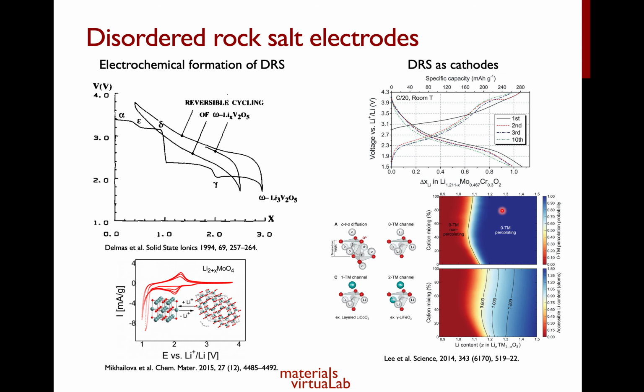Okay. Now, in recent years, the disordered rock salt materials have garnered increasing interest as potential electrodes for lithium-ion battery applications. Okay, so the disordered rock salts are actually not new, right? Even back in 1994, Delmas showed us that if you lithiate the vanadium oxide V2O5, you get a series of phase transformations, and eventually, after you lithiate about 3 lithium per formula unit of V2O5, you end up with what is known as the omega phase of Li3V2O5. Okay, and that phase actually is a disordered rock salt phase.